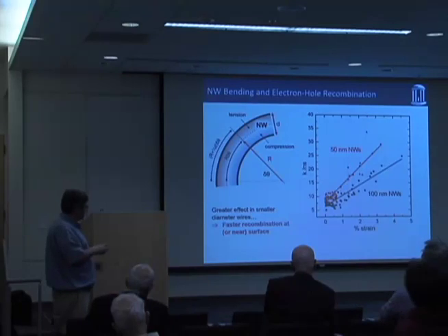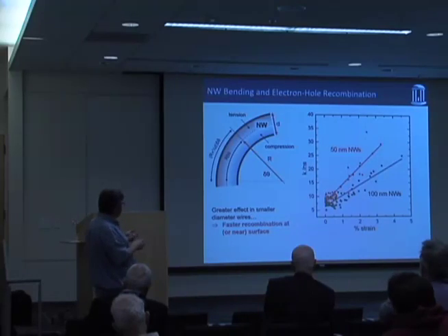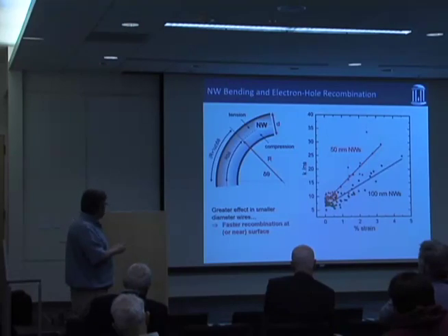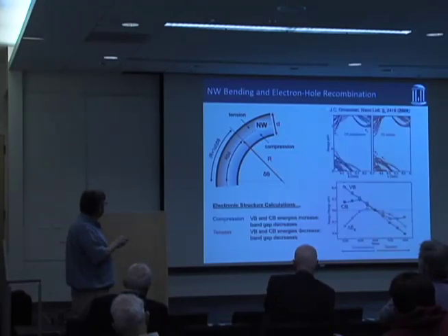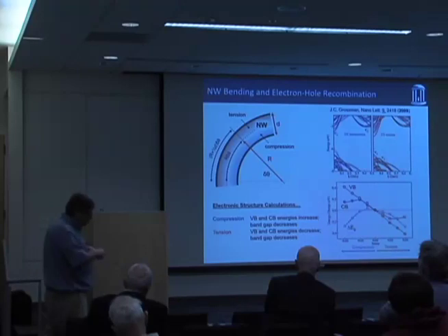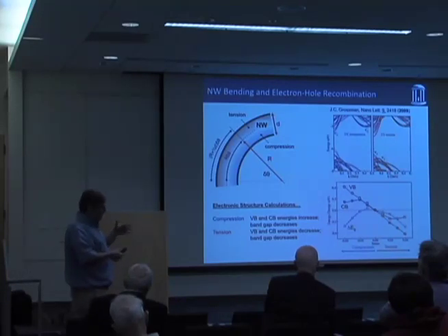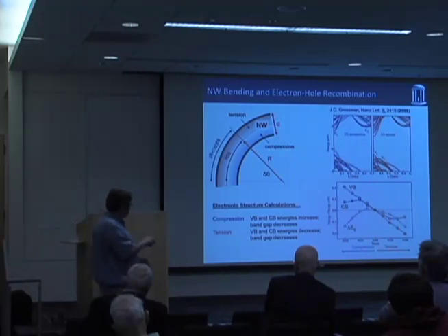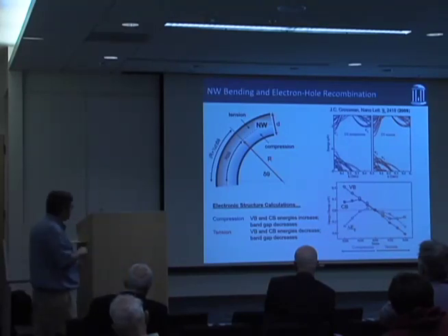And so we started to think, okay, are we just changing defects when we do this? That was our initial thought, that as we bent the wire, we were just introducing defects into it. But it turns out there are some calculations by Grossman's group looking at strain in nanowires and its effect on the band gaps of the valence band and the conduction band. When you strain the nanowire, the band gap actually goes down by about a factor of 2. This is not a small effect. It's over similar ranges, 4 or 5% strain, to what we were seeing in our experiments.